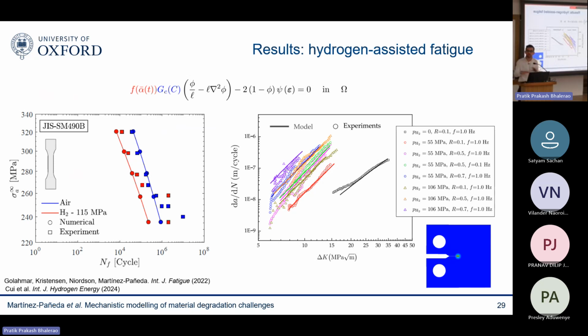And as you can see, we were able to capture all the conditions that have been tested before. If they change the loading frequency, the model will naturally capture that change in loading frequency. If they change the load ratio in the experiments and that increases the crack growth velocity, we will quantitatively be able to capture that effect of load ratio and so on and so forth. So I think a lot of these things are mesoscale processes related to how quickly you load, how quickly hydrogen moves around, and those problems you can naturally capture in these models.